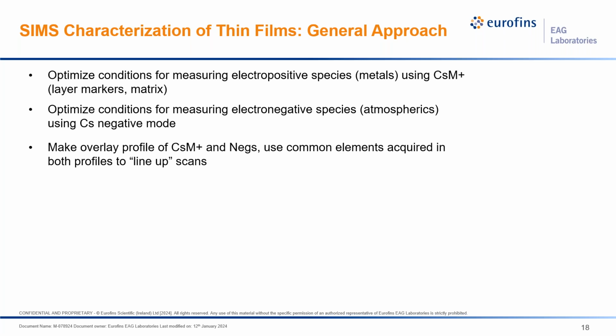We can make an overlay profile of these to get an overall picture of all the different elements that are part of a request. And so then we must line up the profiles to make sure that they display the correct depths, and then we can get full information about our material of interest. This takes significantly more effort than what was considered to be routine SIMS.